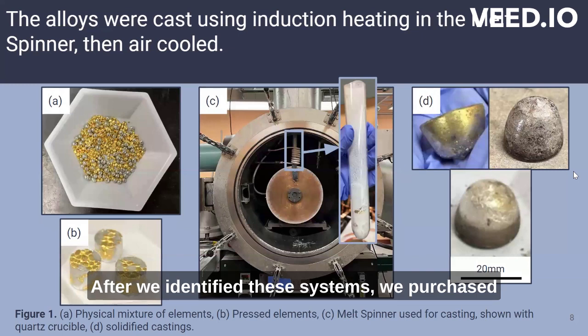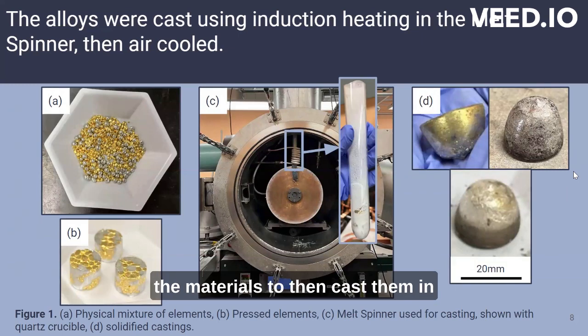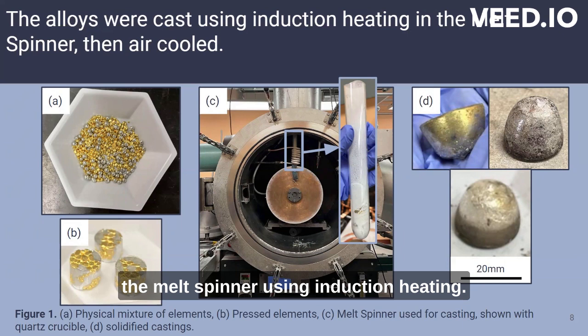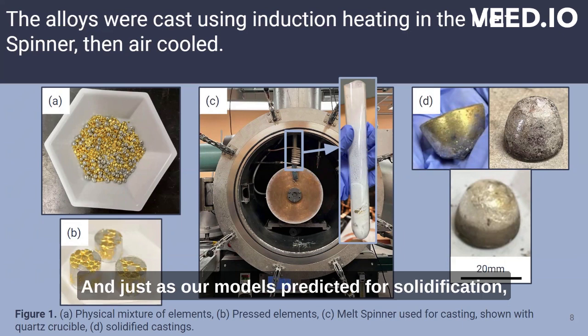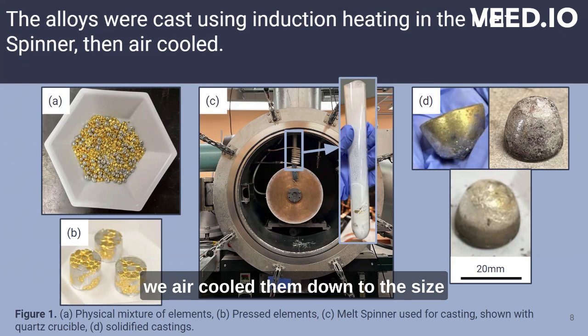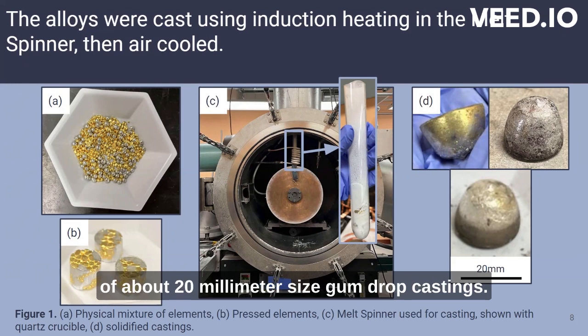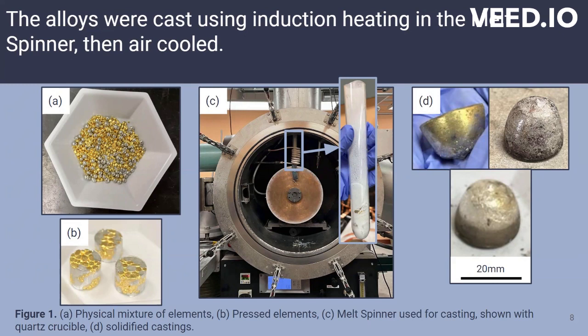After we identified these systems, we purchased the materials to then cast them in the melt spinner using induction heating. And just as our models predicted for solidification, we air cooled them down to the size of about 20 millimeter size gumdrop castings. We then used these to characterize.